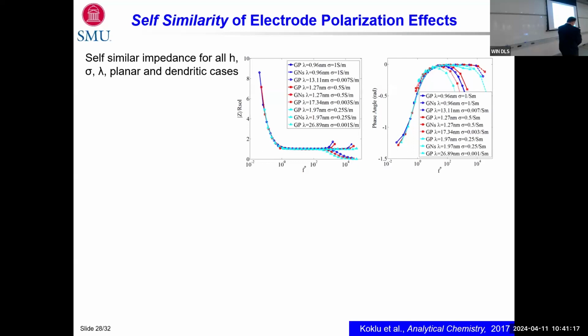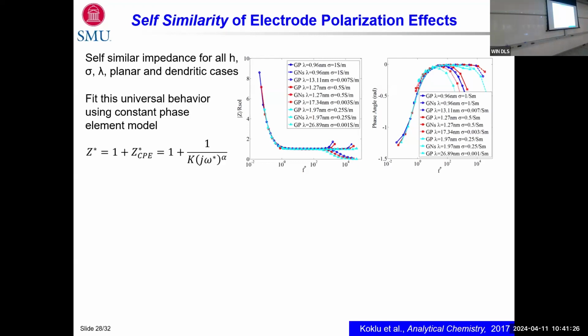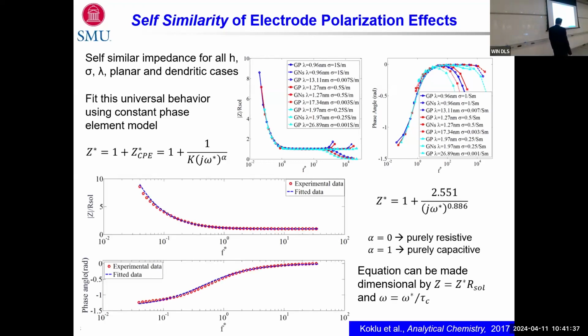So I love that because, as you would remember from your fluid mechanics, it's like the drag force versus Reynolds number curve and so on. So it's showing a universal behavior of some sort. So we modeled that with the constant phase element model, which I indicated earlier in my talk, which is this formula here. What it does is that when alpha goes to 0, it becomes a purely resistive system. Alpha equal to 1 is purely capacitive. And when you get the overall data and fit it, you actually found a formula like that. So this is now a dimensionless formula.